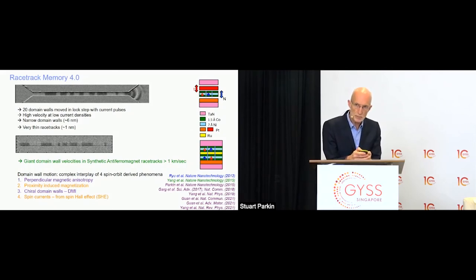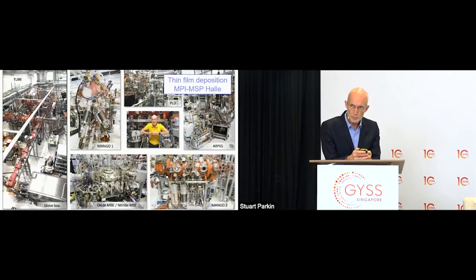This makes this magnetic racetrack extremely useful. Now, I wanted to also mention that to build these devices, we built in Germany a series of deposition systems. On the left-hand side, you can see an orange long tube. Now, these are heating tapes on an ultra-high vacuum tube, 15 meters long. And we can automatically transfer substrates on which we deposit these racetrack films between different types of deposition systems that are specifically designed to use different methods for depositing these ultra-thin layers.